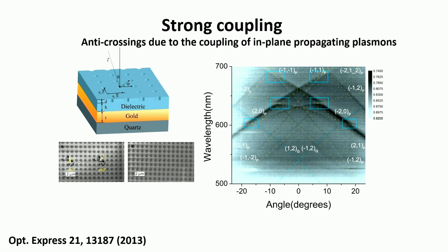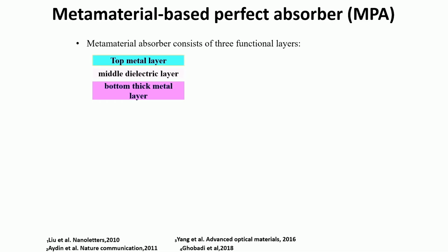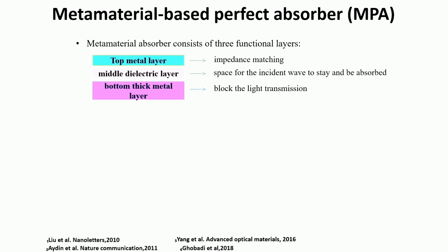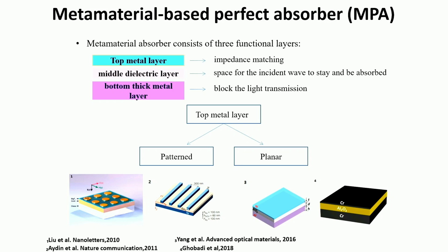Going back to the perfect absorber example, we can have a top metal layer, a middle dielectric layer which is weakly absorbing, and a bottom thick metal layer. Basically, the top acts as an impedance matching layer, then the ground plane or bottom blocking layer is the light reflecting layer, and the middle is the weakly absorbing layer. People have demonstrated different patterned as well as planar designs for these in the literature.